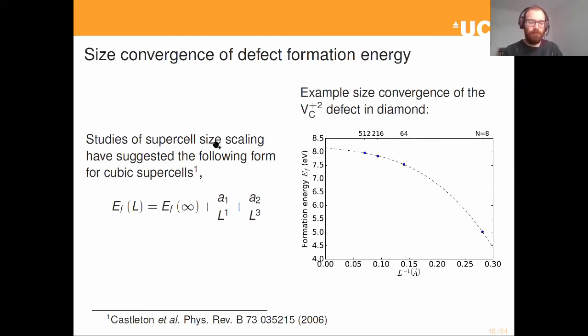In particular, it's often described in terms of an empirical relationship where you have length and volume dependent errors with your model. So this here is a cell with 8 atoms. And we then remove 1 to form the vacancy defect and then calculate the formation energy. And you can see that as we go up to larger cells, all the way to a supercell containing 512 atoms, where we then remove 1 of them to form the vacancy, we see even that is not a fully converged energy.